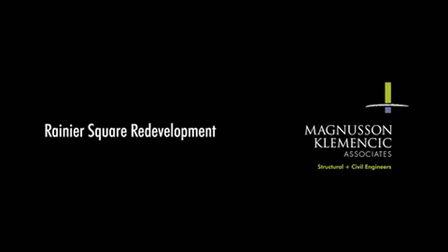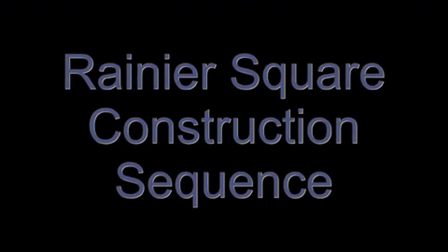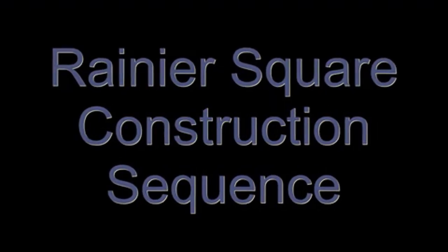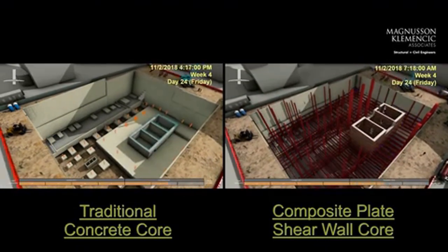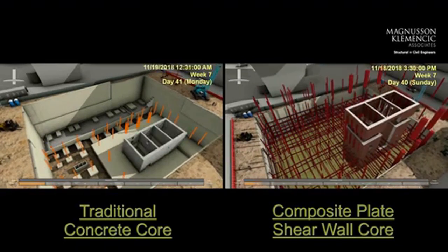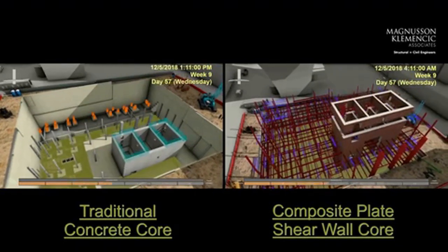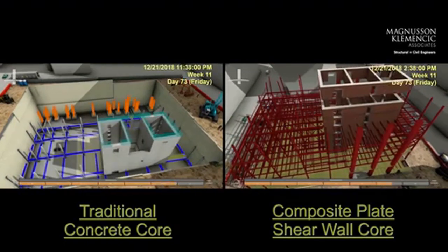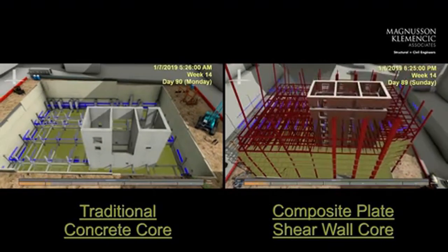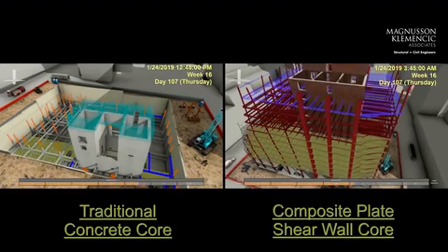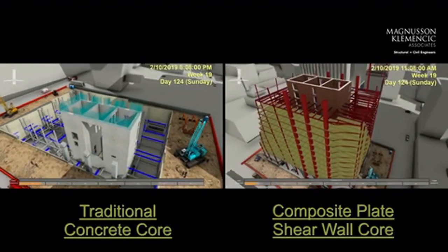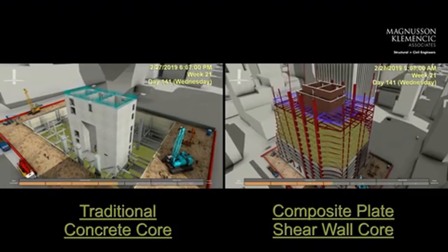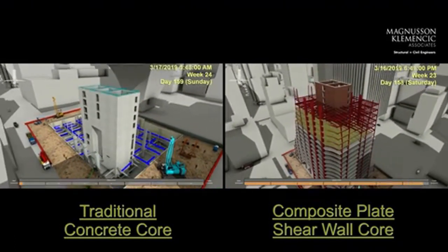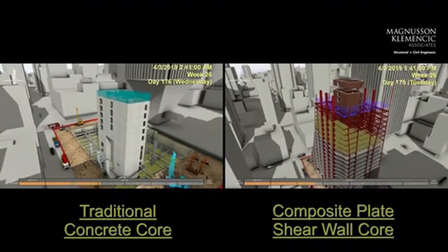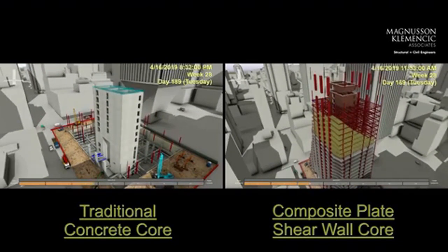Now, we're going to do a quick little video here, and I'm going to talk over this as we do it. On the left-hand side, this is a video we put together before we had contractor input, and we were trying to explain to the owner the potential benefits of switching to the system. So what you see on the left here is the traditional concrete core, the original drawings that we did in schematic design. This was a concrete core with concrete below-grade framing, and it switched to steel framing once we got above grade. On the right is what we proposed in our revised schematic design to move forward with, which was below-grade steel, composite plate shear wall core, the SpeedCore, and trailing operations of concrete. And when we first put this together, there was a difference of about 4.5 months, which we were extremely excited about. And to us, 4.5 months was lofty, and if we could achieve that, we were extremely excited.